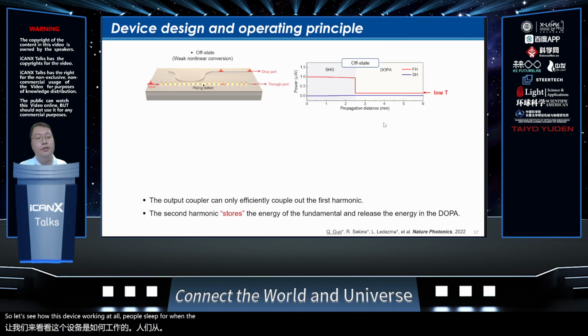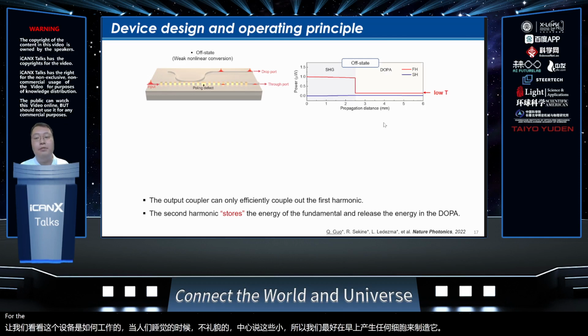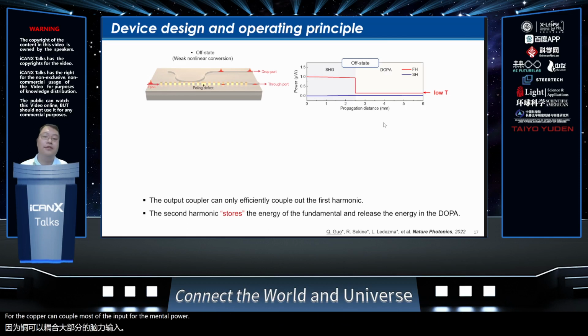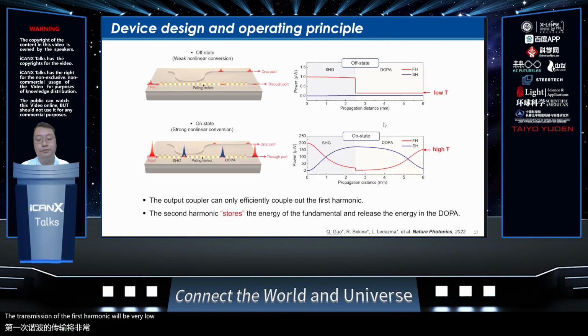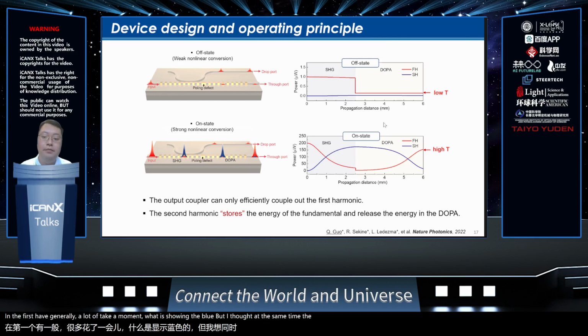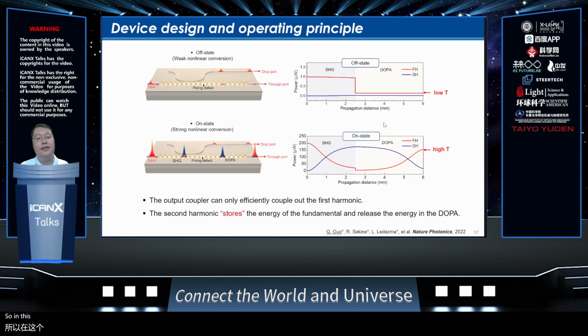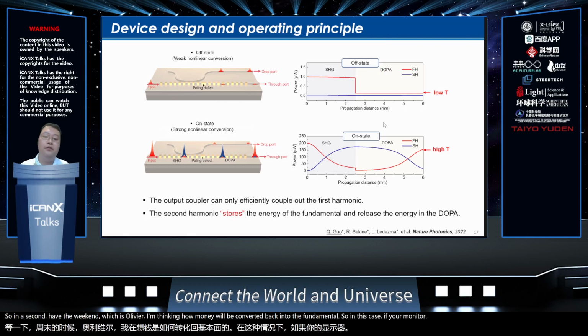So when the input light intensity is small, it barely generates any second harmonic in the main waveguide. So the coupler can couple most of the input fundamental power out. So if you monitor at the end of the main waveguide, the transmission of the first harmonic will be very low. But if you have a stronger input light pulse, in the first half, we generate a lot of second harmonic, which is shown in the blue. But at the same time, the fundamental wave gets depleted. So in this case, the coupler can only couple out a tiny amount of fundamental power. So in the second half of the waveguide, which is the DOPA, the second harmonic will be converted back into the fundamental. So in this case, if you monitor the power at the end of the waveguide, the transmission of the fundamental will be much higher.